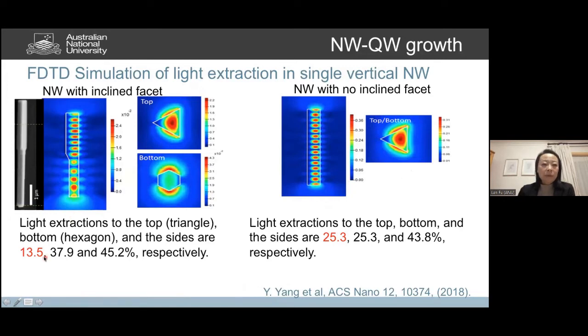So we did an FDTD simulation to compare this quite strange looking inclined facet nanowire with a more uniform faceting nanowire, so two types of shapes. This shape is purely based on our nanowire growth. You have a bottom hexagonal wurtzite indium phosphide nanowire to start with, and then because of the evolution of the facets during the growth, you see a lot of triangular shaped nanowire integrated. We compare that with a purely triangular shaped nanowire.